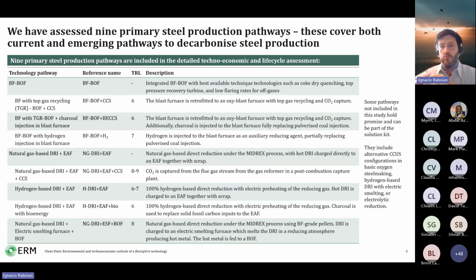For each of these, we model the complete mass and energy balance where, for example, the amount of hydrogen that is injected into the blast furnace is constrained in terms of the energy balance, the fact that from a metallurgy or process engineering point of view, hydrogen reduction is endothermic, so you can only inject a certain amount. The rest has to be with coke or pulverized coal injection and other considerations of that sort.